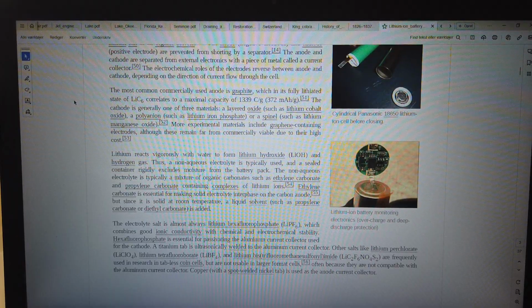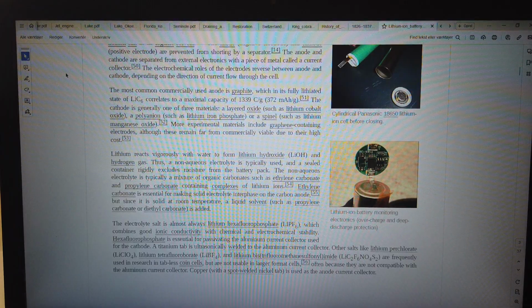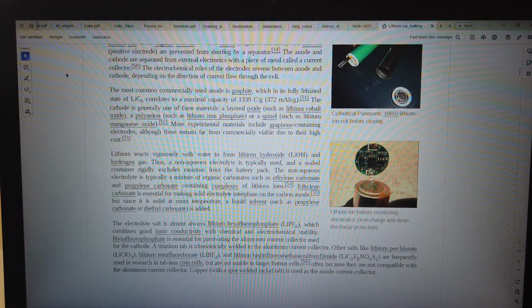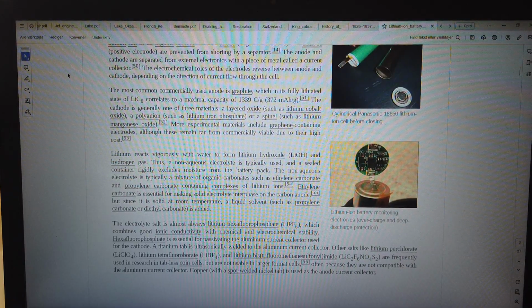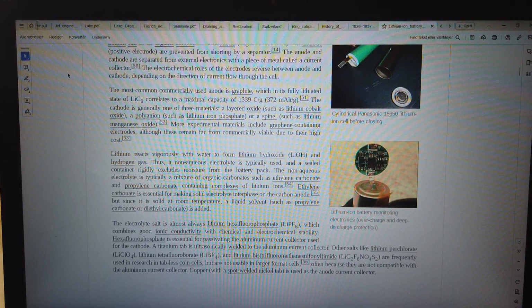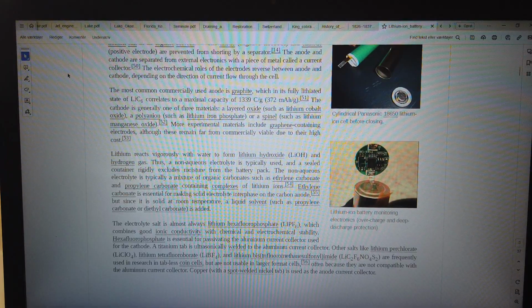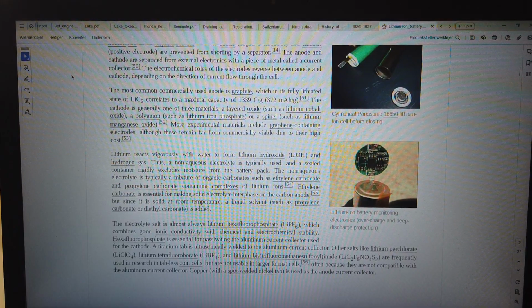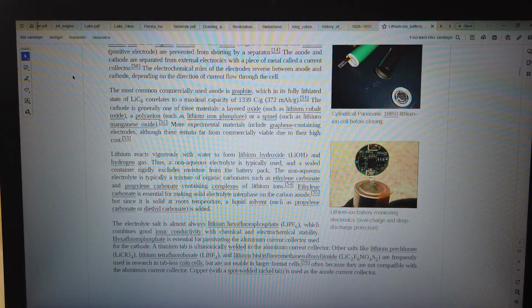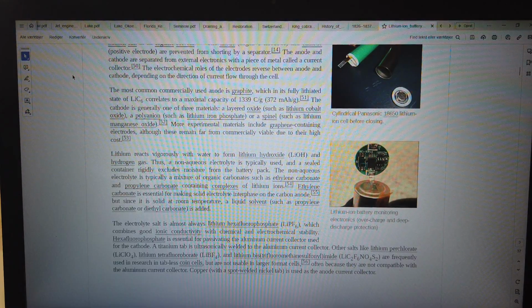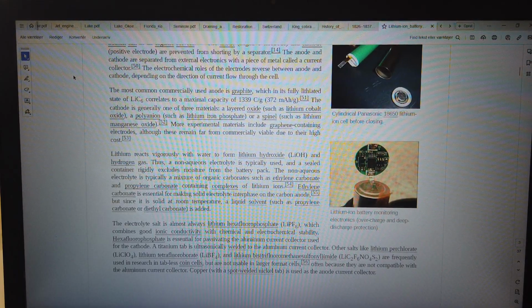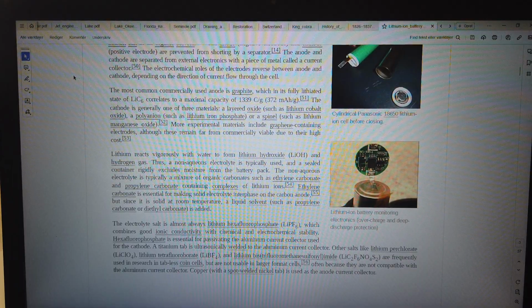chemical and electrochemical stability. Hexafluorophosphate is essential for passivating the aluminum current collector used for the cathode. A titanium tab is ultrasonically welded to the aluminum current collector. Other salts like lithium perchlorate, LiClO4, lithium tetrafluoroborate, LiBF4, and lithium bis(trifluoromethanesulfonyl)imide, LiC2F6NO4S2, are frequently used in research in tabless coin cells, but are not usable in larger format cells, 56, often because they are not compatible with aluminum current collector. Copper, with a spot-welded nickel tab, is used as the anode current collector.